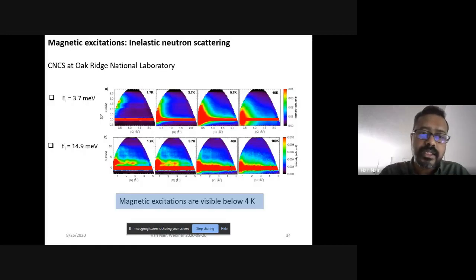Now, if you increase the energy of incoming neutrons to 14.9, you see that the magnetic excitations now extend to a slightly higher Q value, which is natural because you have increased the energy of the incoming neutrons. And you see something similar at 1.7K. And then as you increase the temperature, it becomes very broad and goes away. So there are excitations at low temperature, and they are at about 1 meV and 1.5 meV.